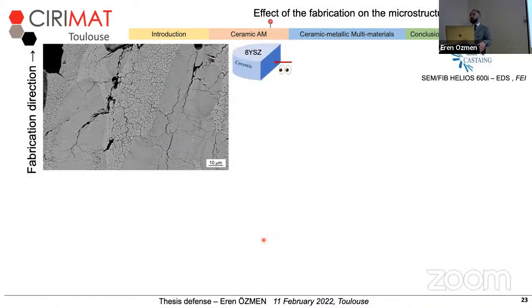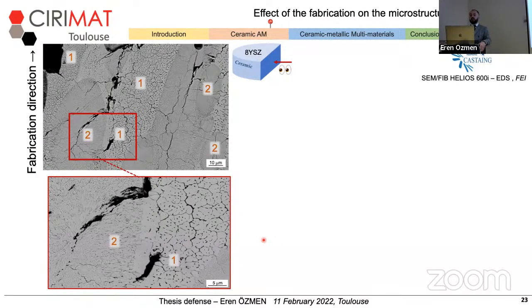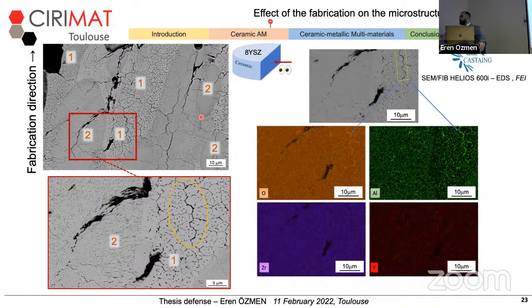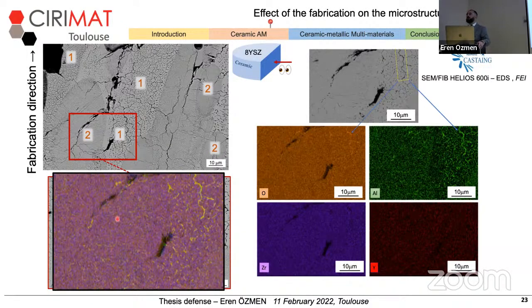So when we observe the cross-section of the ceramics with scanning electron microscopy, we see that for 8YSZ, two microstructures appear in the observed zone. The first microstructure is mostly distributed through the structure with coarse grains, and the second microstructure is mostly elliptical in shape and appears locally inside the first microstructure. To see the distribution of elements in these microstructures, I ran an EDX elemental mapping. And when I overlap all the elements, we see that there is 8YSZ everywhere inside the microstructure. So the first and second microstructures that we identified have the same composition with different morphology.